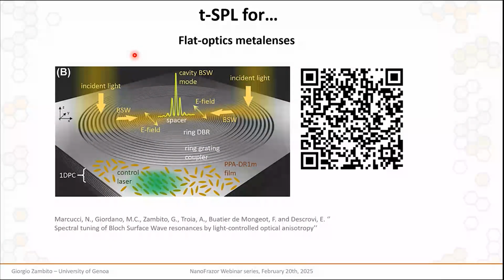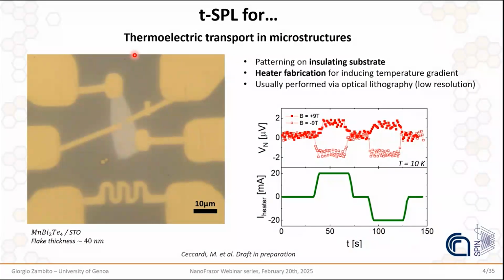And also, as a later work, which is actually still to be published, thermal scanning probe lithography is being implemented for the fabrication of high-resolution metal electrodes on insulating substrates to allow measurements of thermoelectric transport. In this case, it's a kind of measurement and fabrication that usually has to rely on optical lithography, and that limits the level of resolution that you can achieve when you fabricate metal electrodes. As a consequence, the capability to perform a similar lithography at a higher resolution level, thanks to the NanoFrazor, can also be another advantage that this technique gives you.